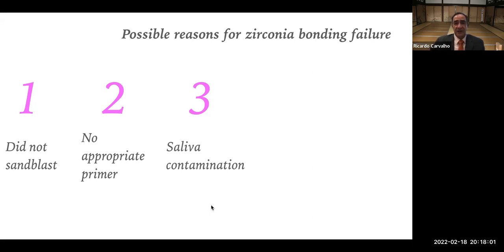Clinically, what we do, we receive the crown, we want to first do the try-in. We want to try the crown, whether it is fitting, or the bridge. And yes, there will be saliva contamination for sure. And we learned over the years that saliva is a very bad contaminant for zirconia, because the organic elements, the proteins in saliva, they react with the oxidized surface of zirconia. So it's not only a contact and then you rinse it, it's clean. There is a chemical reaction there, an oxidation of the surface that does compromise the bonding of the primers. So saliva is a big issue for zirconia, and clinically it happens most of the time.